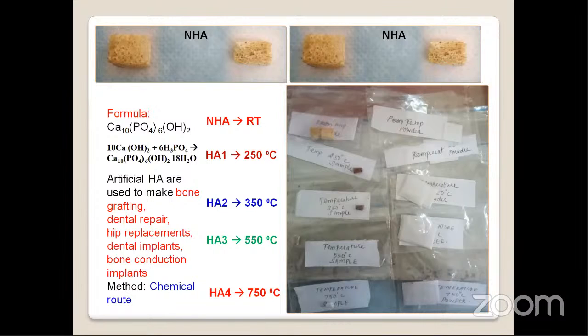So the structure is completely getting varied. So it is understood that the maximum stability of the hydroxyapatite natural bone material is 750 degrees centigrade. After that it will be like ash. That's a different phenomenon, we'll discuss later. After the preparation of these samples, we need to grind them and take them in powder form. See, these are the powders. The adjacent figure shows the powders of these hydroxyapatite materials at different temperatures.